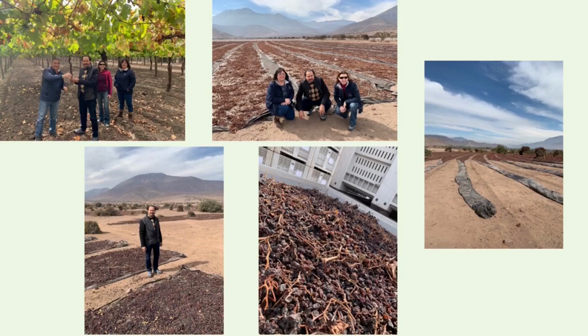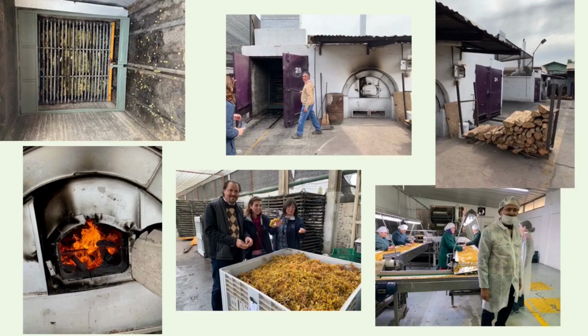And then when you go to Chile, they dry in the sun, like you see, they just lay them on the ground, very dry, for a number of days, actually 2-3 weeks, and they dry the raisins there. And then finally they process, final drying. And some of the varieties, they dry at 70 degrees Celsius. They use wood, timber, to get the fire, and then they dry on that fire. And that variety, the yellow variety, has no issue of crystallization. That variety doesn't have it, and they didn't know why. In that variety there is no problem, but in other varieties we have the problem.